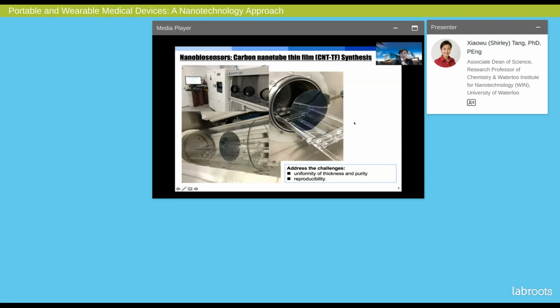This is the actual system for the synthesis. This is a low-pressure chemical vapor deposition system. This is not unique to nanotube synthesis. As a matter of fact, this is commonly used in the semiconductor industry. Therefore, the synthesis process we have is readily scalable, and it provides uniformity in terms of thickness and purity in our nanotube thin film, and is highly reproducible.